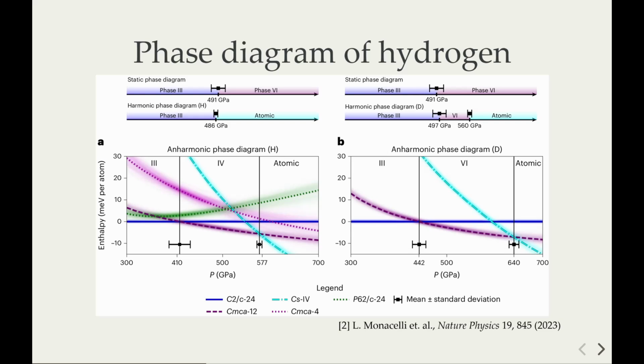When we switch on anharmonicity, the phase diagram changes again qualitatively. Phase 6 appears stable in a wide region of pressure. It's 160 gigapascal, so not negligible at all. And hydrogen's atomic phase is pushed toward higher pressure, so very difficult to reach, probably reachable in the future, not in the next 10 years probably.